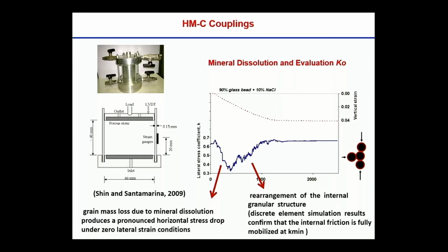And it is an oedometer cell that was built. In fact, we built this kind of model, and we also performed these experiments, initially with this material, and now we are doing them with our artificial carbonate. In this test, we have the sample here. We apply a constant vertical stress, and the lateral displacement is constrained. We have a strain gauge here that is able to measure the horizontal stress, the lateral stress.